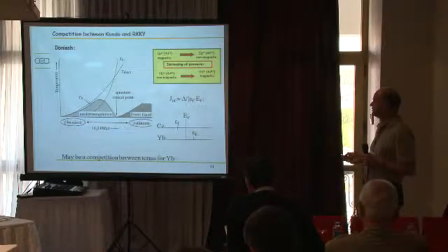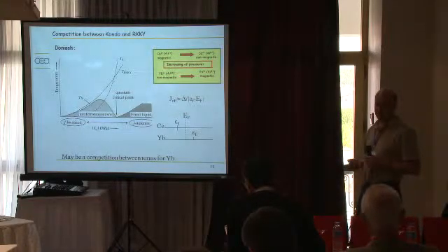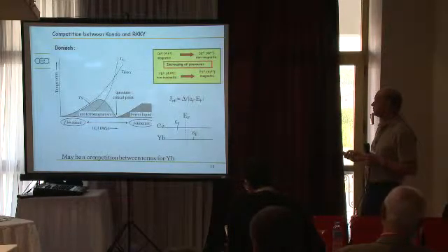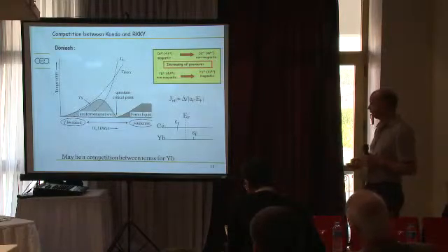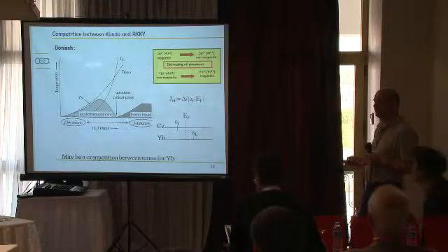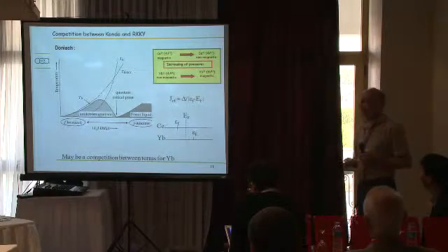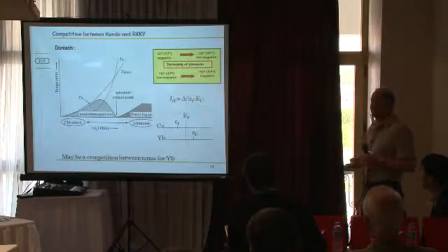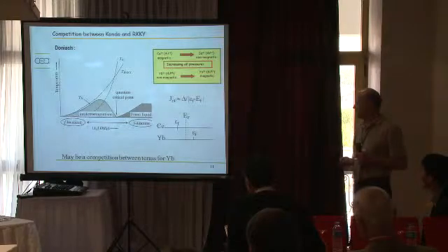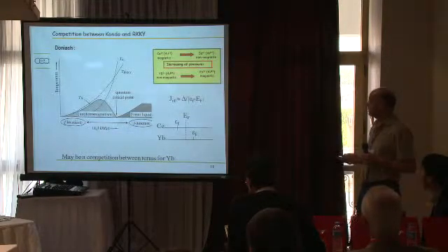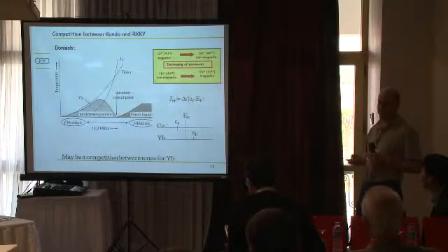But we can wonder what will happen if, now, what I didn't say is that the energy of the 4f electron is obviously closely linked to the valence. So now we re-establish the link between the two pictures. We can wonder what will happen if the valence reaches a state where it no longer changes with pressure. If, for example, we reach a completely trivalent ytterbium 3+, probably epsilon F will continue to vary with pressure, but much more slowly. And so you can imagine that the effective pressure would become much weaker. And in an extreme case, it could even be the increase of delta which dominates, and J could actually start to increase again with pressure.